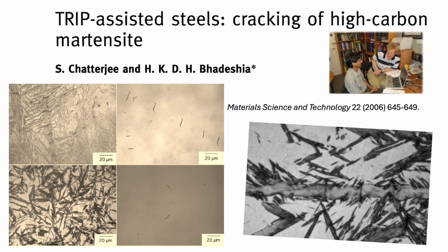Okay, clever. So they varied the grain size from big to small. Yep. They went from about 1200 degrees C, which gave quite coarse grains around 410 microns, all the way down to 950 C, which resulted in really fine grains, only about 25 microns across. Quite a range. And then they quenched them all to form martensite. Right, creating that brittle, high-carbon martensite, but within different sized parent grains. Then they looked closely under the microscope. And what did they see?